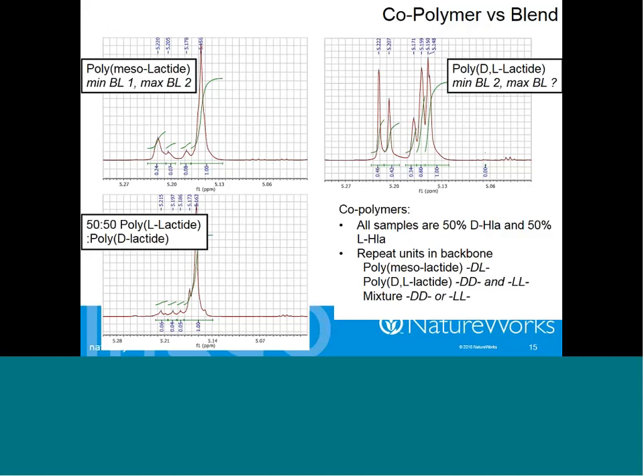The spectrum on the upper right is a poly-DL or poly-rac. That would have a minimum block length of 2 if it were rigorously alternating, and could have a maximum block length of just about any number you pick. As I mentioned, if that block length gets up above 40 or so, a polymer made from rac-lactide will look an awful lot like a stereocomplex material. And then the NMR spectrum on the bottom left is a spectrum of poly-L and poly-D lactide, so that would be a spectrum consistent with stereocomplex PLA.